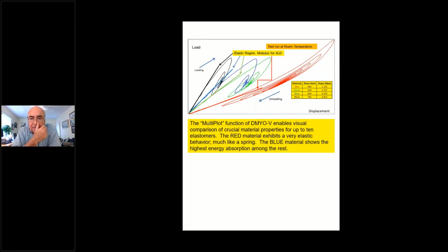In this case, we have 4 different Shore values, 40 to 70, and each one has different slope, as we reported. The red, which is more elastic than the others, has a slope of 1.125 megapascals. So then comes green, which is 2.707 at 50 Shore A. Then comes blue, 3.5, and black at 4.8. These are different slopes. Actually, the slopes are taken in the linear region, meaning right about here. And these are the linear. And we relate this to crosslink density relatively measured. That's what we think is very important to be able to figure out. Not an absolute measurement, but a relative measurement.